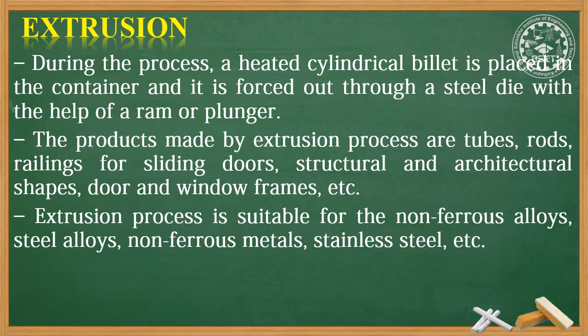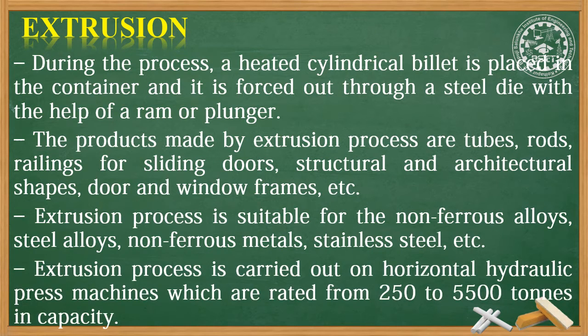Extrusion process is suitable for non-ferrous alloys, steel alloys, non-ferrous metals, stainless steels, etc. The extrusion process is carried out on horizontal hydraulic press machines which are rated from 250 to 5,500 tons in capacity.